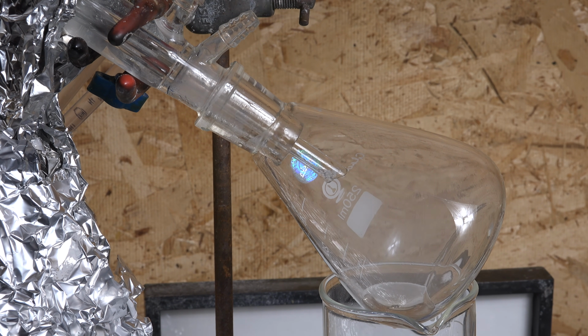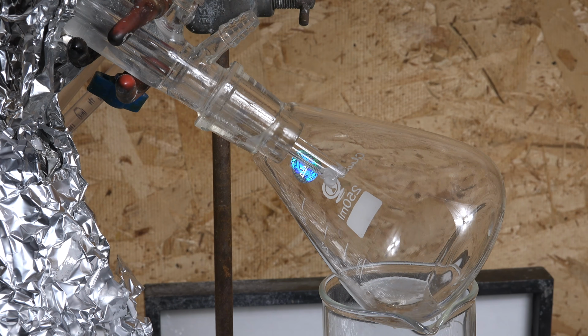Interestingly, the sulfur trioxide that first condenses is the gamma form, which is liquid at the 21 degrees my lab is. But it polymerizes into the beta and alpha forms, which are solid. And you can see the polymerization happening at the end of the condenser here. You can also see the pool of sulfur trioxide at the bottom starting to polymerize as well as it cools. In this run, I produced enough sulfur trioxide that it actually solidified and blocked the condenser.